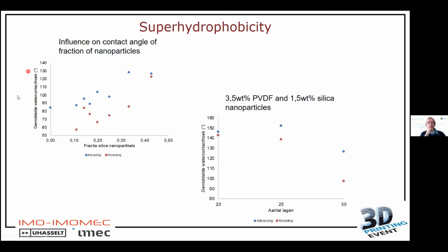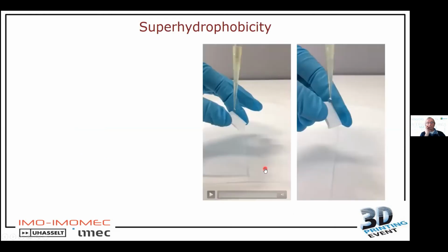Here you see the water contact angle for the amount of silica nanoparticles you have. And as you can see, we would like to go to this 150, and we have to go to very high amounts of nanoparticles. Here, for example, you see 3.5 weight % of PVDF and 1.5 weight % of silica nanoparticles, and then we show that between 20 to 25 layers, we go above this 150 as contact angle for our water. So is this then super hydrophobic? Well, let's show it in a video.